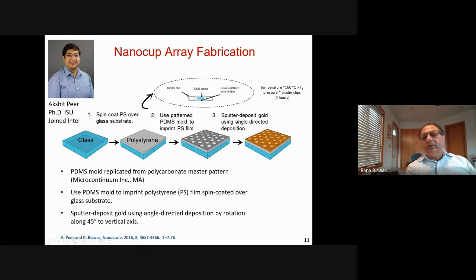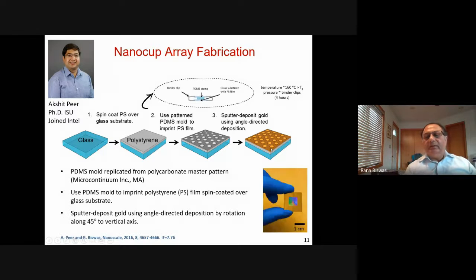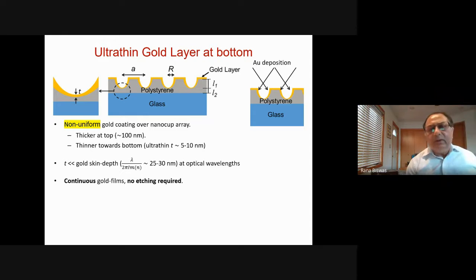So once we do that, we sputter deposit gold on this array of nano cups here on the polystyrene film. Now, this results in samples you can see that are more than 1 centimeter across. So it's very convenient to do measurements on such large area samples using just normal spectrometers. Now, the gold deposition is a little bit different from what most people do. So, what we do is we do the deposition at 45 degrees, and we also rotate the sample. And this results in a coating both on the top and on the side walls.